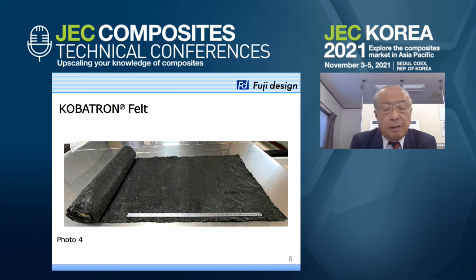Newly developed is non-woven fabric felt, and the width is 1 meter, and this has already gone into production. And normally it requires some additional fiber support to make a dry felt. But in our case, we can control the sizing effect very well. So we can make 100% recycled carbon fiber felt for mass production.